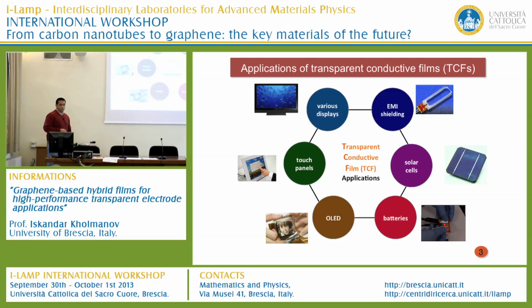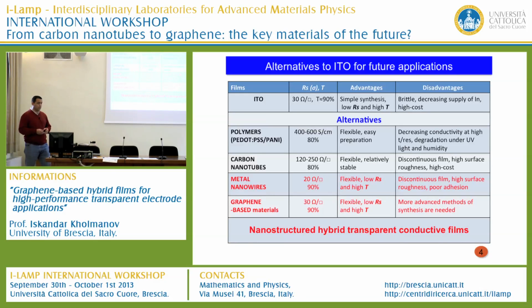This slide shows some of the many devices where transparent conductive films are used. Mostly the large area transparent conductive films are used for various displays and touch panels and also solar cells. About 90% or even higher of the TCF market today uses ITO as a transparent conductive film. ITO with about 30 ohm per square sheet resistance and transmittance of about 90% is now commercially available and is used in different devices.